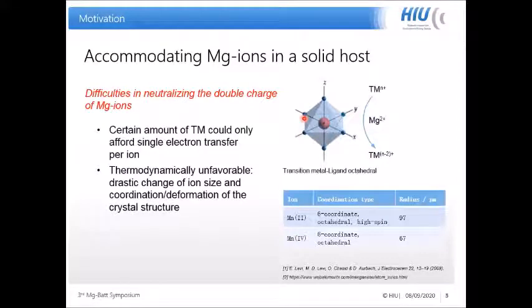Also, even if they have the capability, there will definitely be a drastic change of the ion size and coordination. Here I show you an example of manganese. We see that manganese 2+ has an ionic radius almost 50% larger than manganese 4+, if we consider both of them in an octahedral coordination environment. And this drastic change will of course lead to a deformation of the crystal structure, which is unfavorable for further cycling.